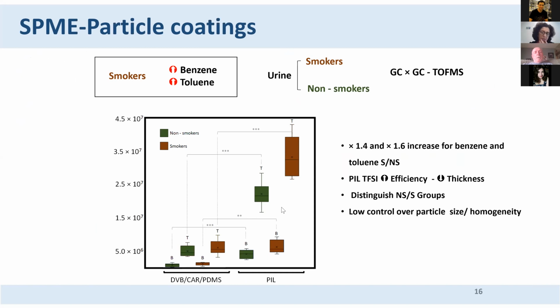And it was quite interesting to see here we use the commercial fiber DVB CAR PDMS. So it's a fiber that is carboxen. And it is very interesting to see that we have, at least for toluene, a much better detection limit than the commercial fibers. And it's also interesting to see that we can distinguish smokers from non-smokers. So this was just for fun. We did it just for fun to see how bad or how good were these fibers with the particle size.